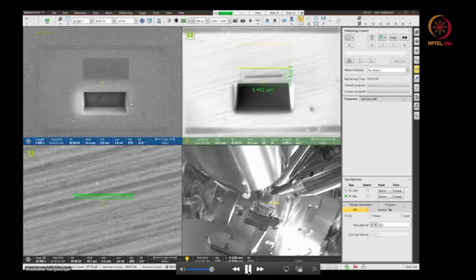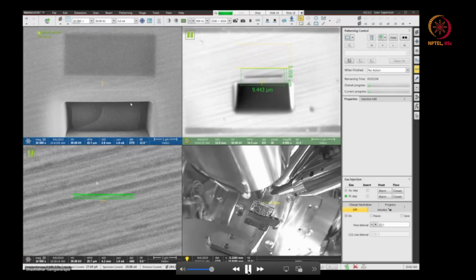Now you can see in the e-beam window that it is now trenching at the top, and the bottom is already trenched because this is 180 rotated. Now the top part is trenching. The same high energy gallium ion is removing material, and it takes the same time, around 1 to 2 minutes. The time depends on the current value. If you use a high current, it will take less time. If you use a low current, it will take more time. So if you want to do trenching, you can use the high current. But one thing you have to check in the I-beam column is that you don't unpause it at a high current value.